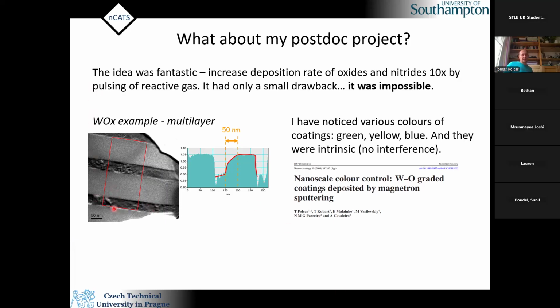So this was tungsten-rich, this black part, and it's very thin. You see this is 50 nanometers, so you get about 50 nanometers of tungsten. Then we get some kind of oxide, which was a gradient oxide, not quite complex. And then again we got a multi-layer structure, not really a homogeneous coating. So we failed, the project failed.